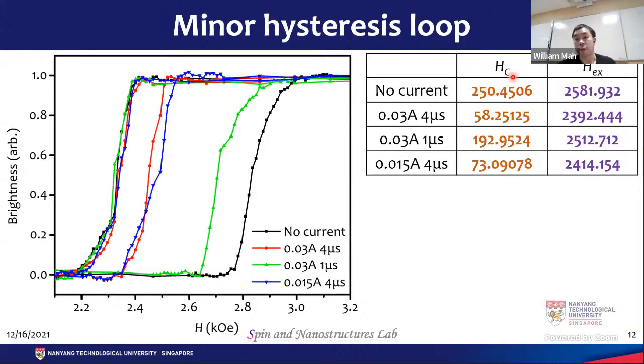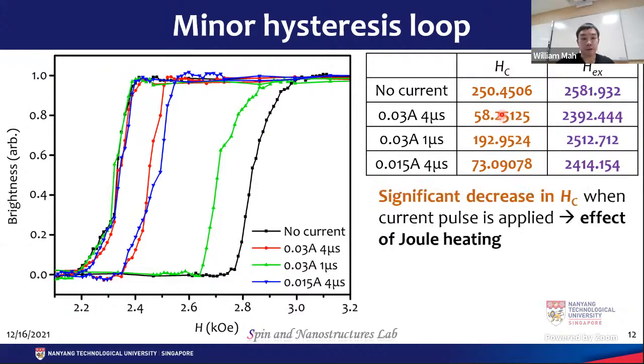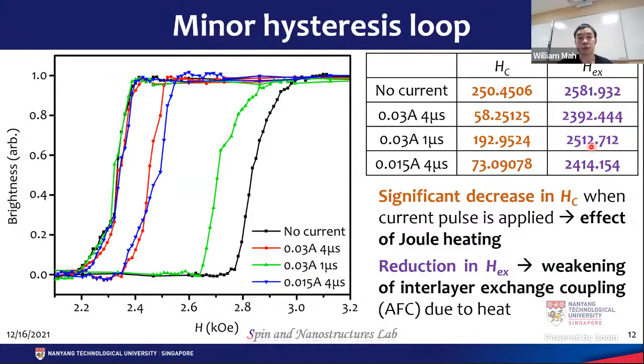If you take a look at the changes to the coercivity, you realize there is significant reduction in coercivity, which is an effect of Joule heating. And if you look at the exchange field, albeit the change isn't as significant as coercivity, there is still a reduction nonetheless. It's reduced, which means there is a weakening of the antiferromagnetic coupling between the top and the bottom layers. That can also be due to heat.